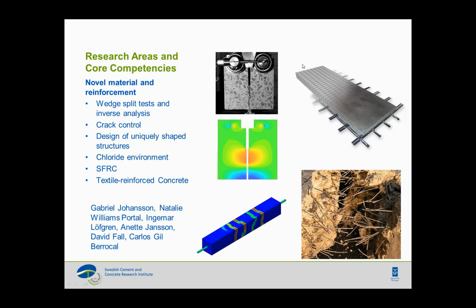So we work with test and simulation at the material level, like this example for a wedge splitting test. We work with specimens in different environments, such as in corrosive environment, and look into how corrosion or chloride penetrates through the concrete cover, and when such a specimen is loaded, how the crack widths and crack distribution is influenced. We'll look into steel fiber reinforced concrete, and we'll look into different material properties of this material, and also we work with textile reinforced concrete.